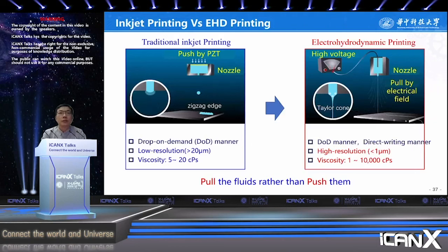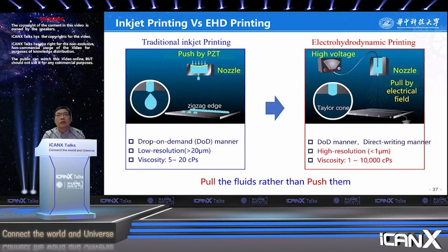Usually the traditional inkjet printing fabricates structures in a drop-on-demand manner. The printed structures usually have zigzag edges, so they are not suitable for stretchable electronics. At the same time, there is a strict limit on the ink for traditional inkjet printing. The viscosity is merely from 5 to 20 cP. The resolution is larger than 20 micrometers.